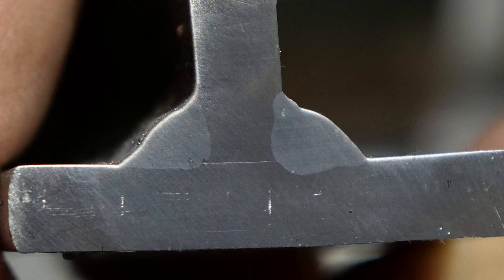I metered it and it was around 182 amps, so I was up there on output. I just couldn't get enough wire feed to really make this work better. Other than a couple little bits of porosity, little pin dots, the weld itself has the penetration, so that's good. Let's move on and look at the 3/8 plate comparison.